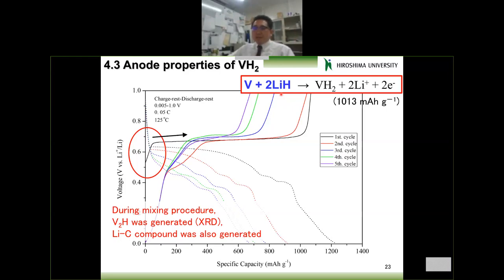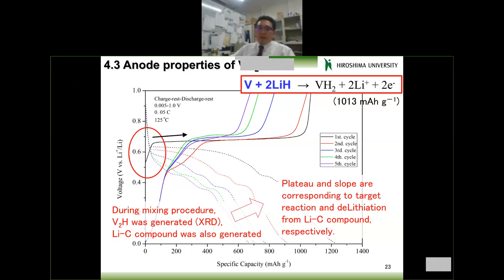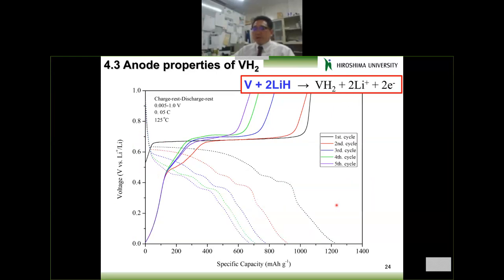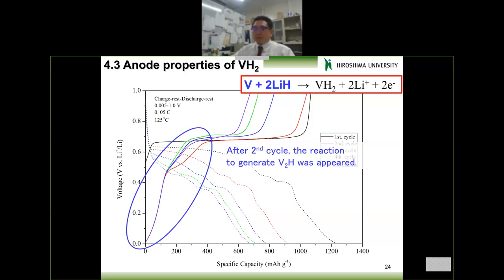Then quite a high capacity was observed, because the theoretical capacity is about 1,000, but this shows more than 1,000, even with some 25% capacity loss due to this vanadium 2 hydrogen. Okay, but actually this much larger capacity can be explained by this lithium carbon compound. The plateau and slope correspond to the target reaction and delithiation from the lithium carbon compound respectively. So somehow we can understand this reaction through all this investigation. Okay, and then after the second cycle, quite a similar profile is observed.